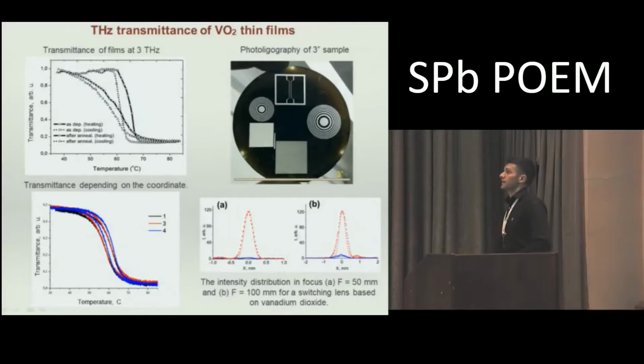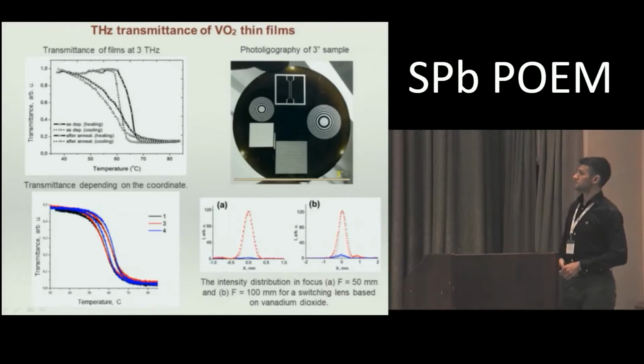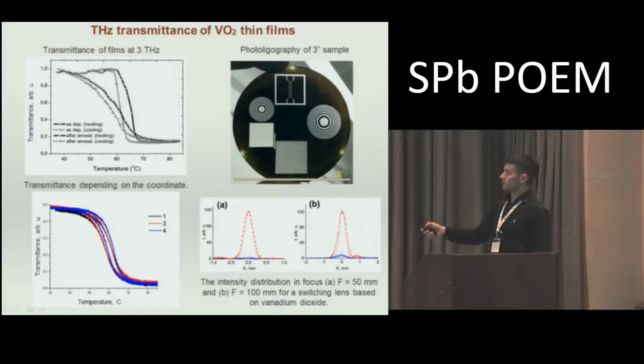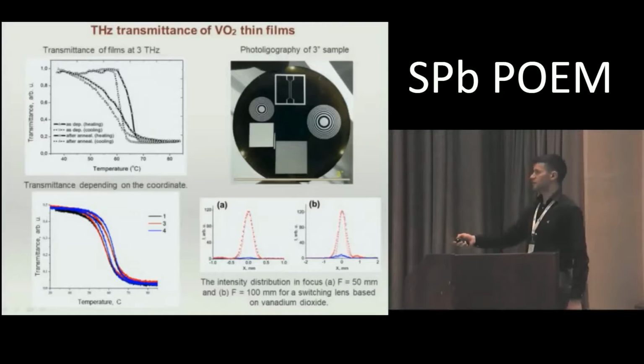The same we have for the terahertz transmittance of vanadium dioxide thin films. Here we have hysteresis for two different samples, without annealing and with annealing. We see that the hysteresis is wider for samples that have smaller grains and a lot of grain boundaries than for the annealed sample. There is also no dependence on the radius for these samples, so we have almost the same change in the transmission of terahertz radiation in our samples.